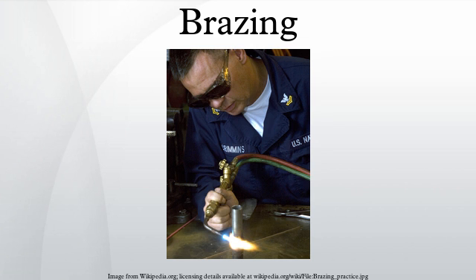Brazed hard metal joints are typically 2 to 7 mils thick. The braze alloy joins the materials and compensates for the difference in their expansion rates. In addition, it provides a cushion between the hard carbide tip and the hard steel which softens impact and prevents tip loss and damage, much as the suspension on a vehicle helps prevent damage to both the tires and the vehicle.